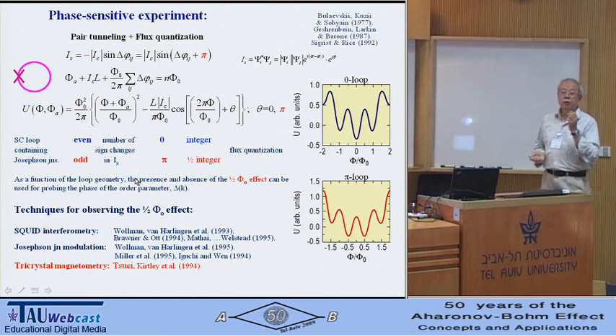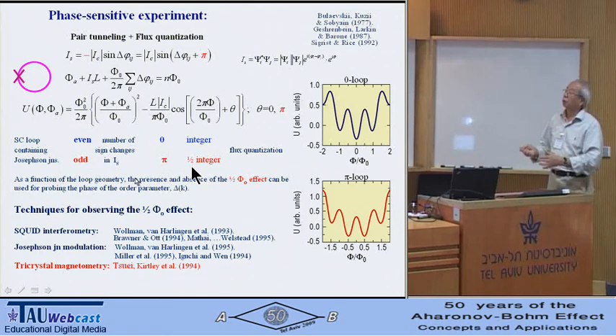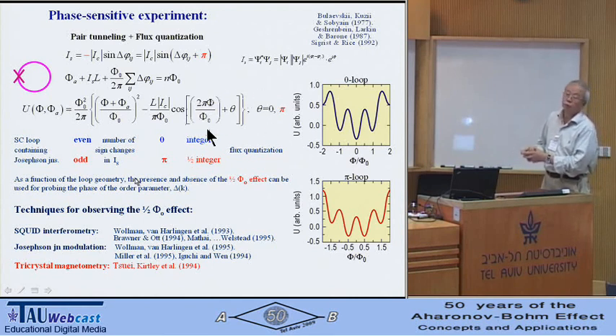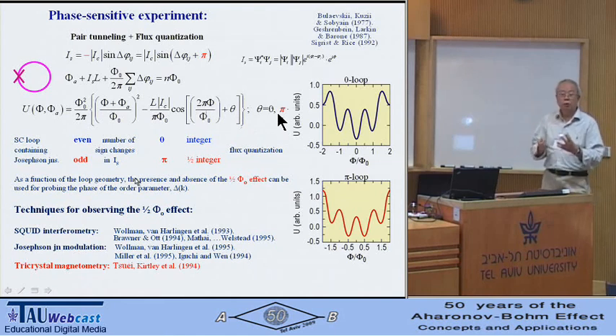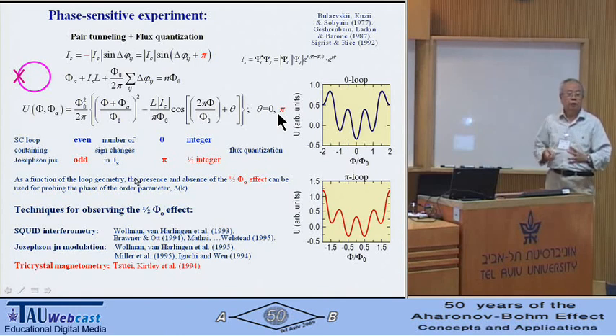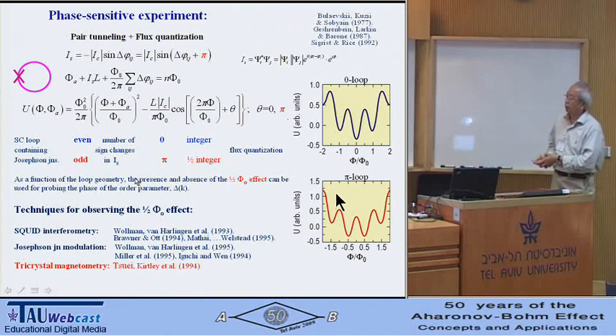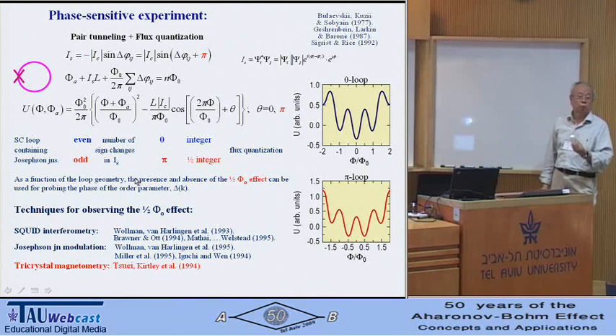Now, if the sign change is an odd number, then you get a net phase change of pi. The system would be frustrated and it wants to compensate the energy of the Josephson junction, as you put a pi in here. And that will cause the system to spontaneously generate a current. That produces a half-flux quantum. Here you have a plus or minus half-flux quantum threading the loop.